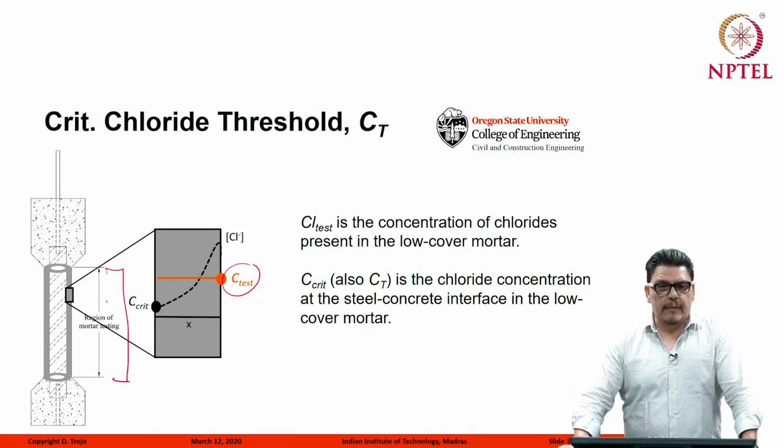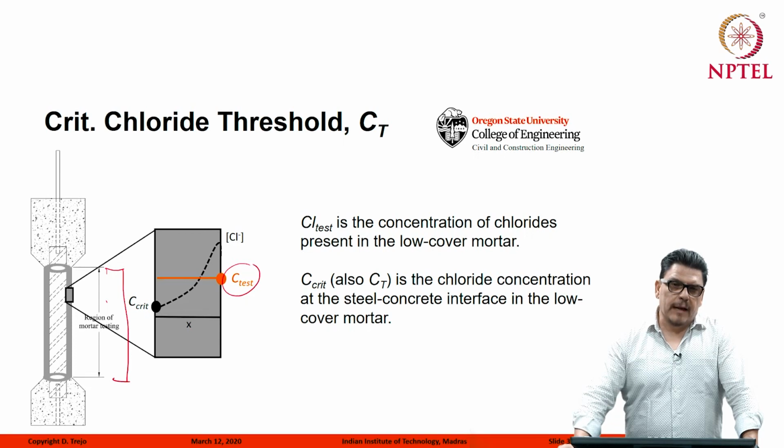I'm not going to show it now. It's very repeatable. It seems to run about 60 to 70% of the average value. So our C-crit is about 60 to 70% of our C-test.